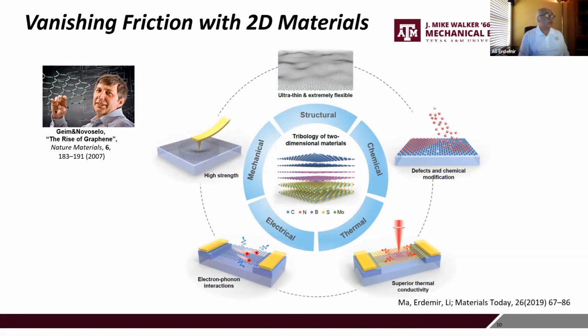So we were one of the very first to actually start rubbing and scrubbing graphene, and we published some very good papers, a number of papers, which showed indeed even one monolayer of graphene would provide very long wear life, despite having very high contact pressure. And there was also the possibility of further functionalization of graphene to achieve nearly zero friction.